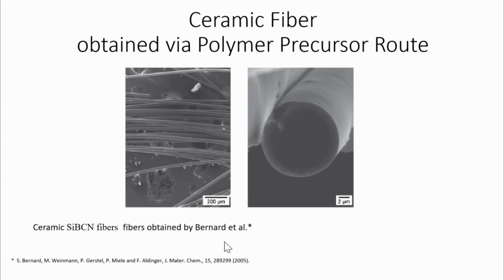The fibers exhibit a tensile strength around 1.3 GPa and a Young's modulus around 172 GPa. The ceramic fibers retained their amorphous character until 1700 centigrade. And using these techniques, it's possible to obtain not only micron-size materials, but materials with a much lower size.